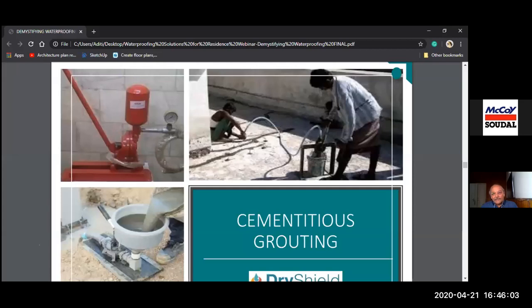It has crystalline admixture added to it. It has fibers in it, and it's injected at high pressure. Now, something like this goes inside, and here we are doing it because there is already seepage in the wall. If seepage is in the wall, from inside it is wet. There is moisture. So when you use a product which has crystalline admixture inside, and it goes into the wall, it reacts very fast.